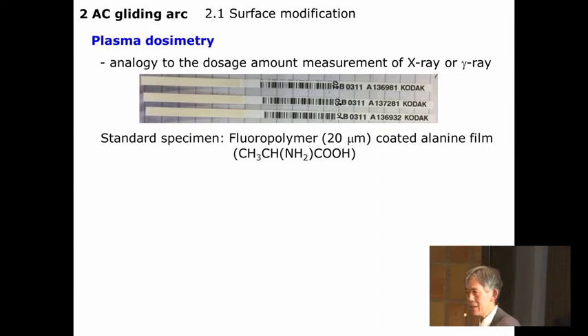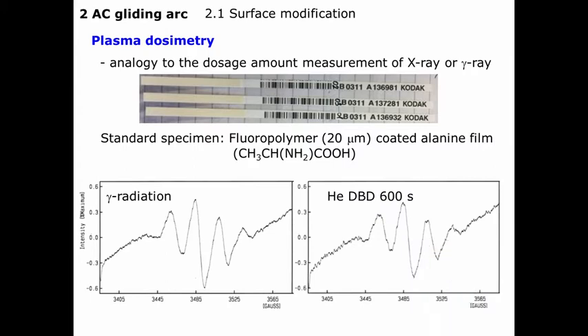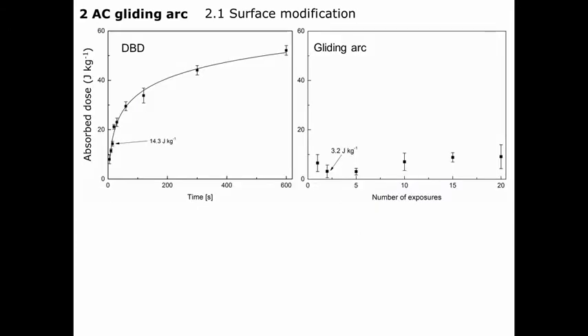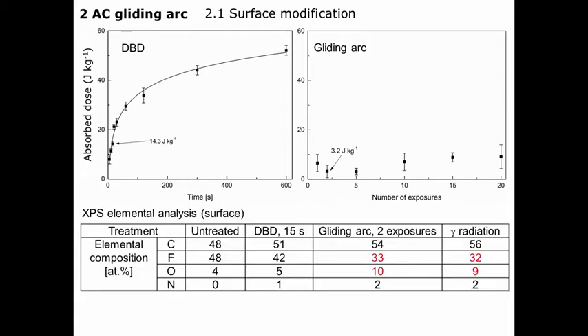It's not gliding arc on this page, it's with DBD. Then we had a clear fingerprint or indication of creating radicals in the alanine. It was quite surprising, and I was a bit in doubt about it until the end of my research. But then, obviously, I compared the effects with DBD and gliding arc, and then saw a very huge difference between them. For this specific condition, DBD can affect the property of alanine beneath the very thick fluoropolymer, but not the gliding arc. But on the other hand, if it is surface, it's quite different.